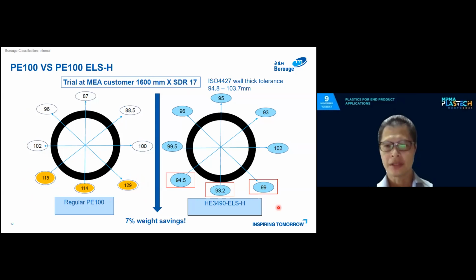Under the same condition, this ELSH material has been extruded, and you can see that the wall thickness at 4 to 7 o'clock is less than 103.7 mm. It does not exceed the maximum tolerance provided in ISO 4427. Of course, you can see that some of them are still outside the range, less than 94.8. But achieving 94.8 is easier than having a high thickness and reducing it to a smaller wall thickness.